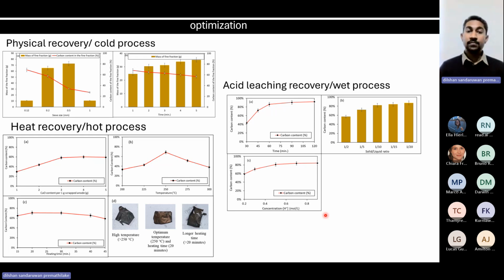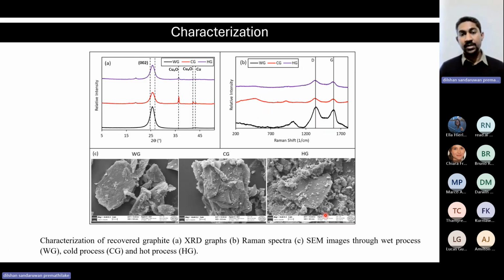And then I moved to the characterization of these three different materials that I recovered from anode active materials. You can see that the CG and the HG stand for the cold process graphite and the hot process graphite. You can see that many impurities are still available in both of these graphite samples. This is because the methodologies that I used are not good enough to remove all these impurities from the final graphite product. However, in the wet process graphite, where I used aqua regia, you can see